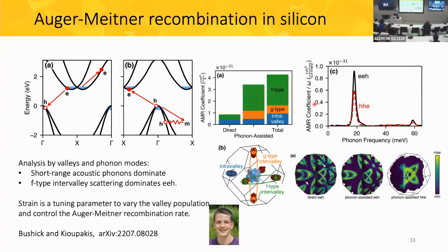Another thing we can analyze with our calculations is which electrons, which valleys, and which phonons participate. What we see is that the dominant phonons that matter here are the short-range acoustic phonons of silicon, with a frequency of 20 meV. When it comes to the valleys of the two electrons, they can be in the same valley, in valleys opposite of each other, or in valleys perpendicular to each other. We find that the perpendicular valleys dominate, which tells us that by using strain to change the relative energy of these valleys, we can potentially tune and engineer the Auger-Meitner recombination rate in silicon. So again, this is the work of Kyle, and you can see details on the arXiv.